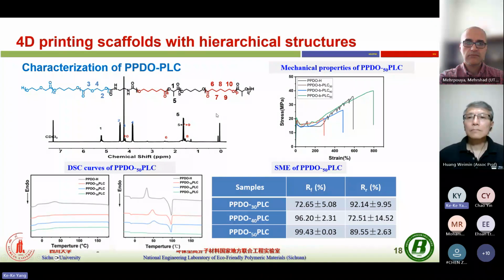After two steps of synthesis, we can characterize the structure, and we find the mechanical properties of this copolymer can also be tuned by the composition, as well as its glass transition temperature and crystalline behaviors. Based on the optimized composition, we find this material can show good shape memory effects.